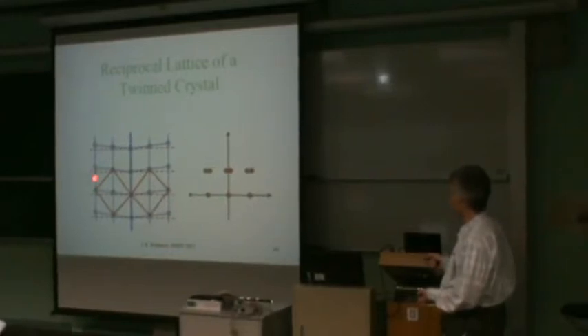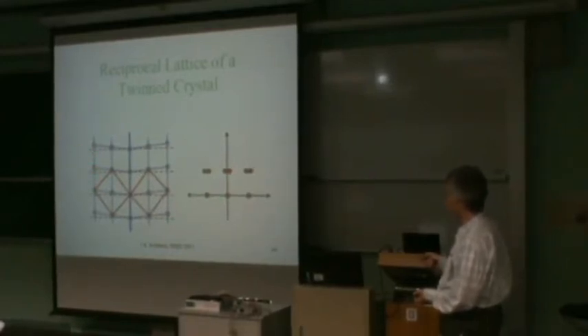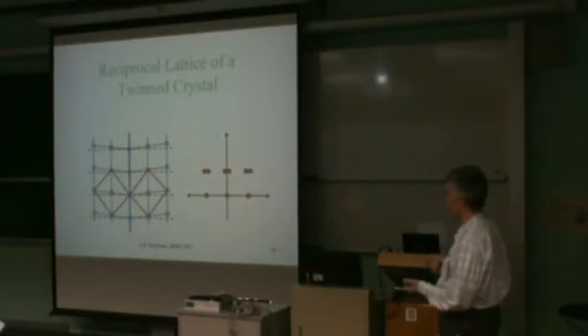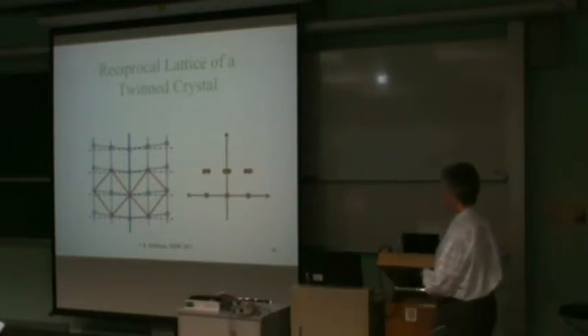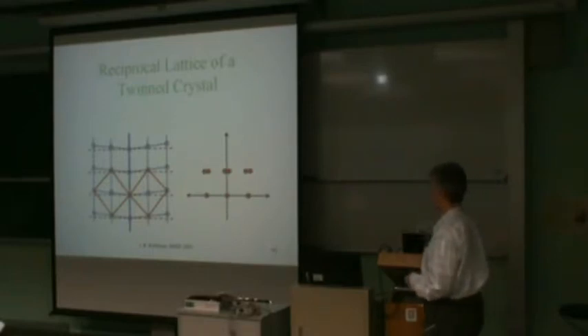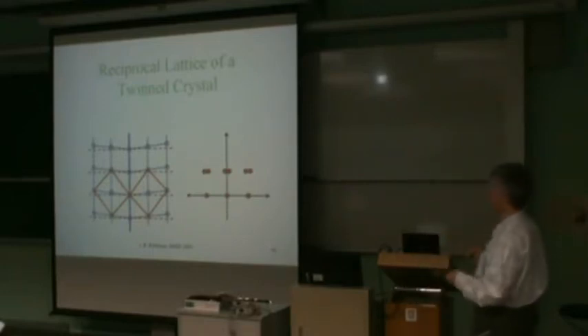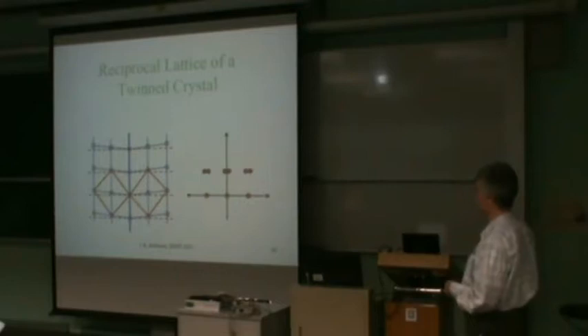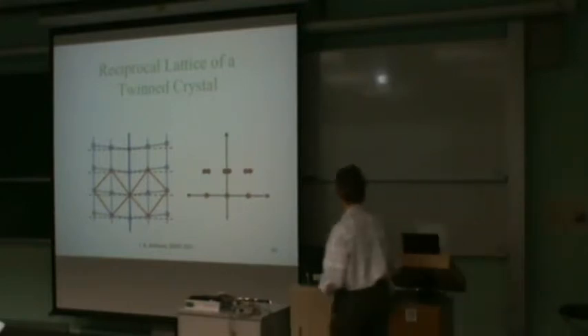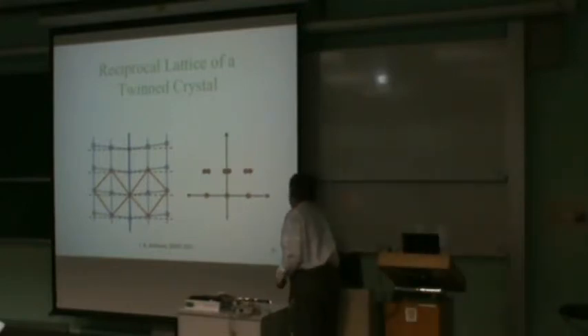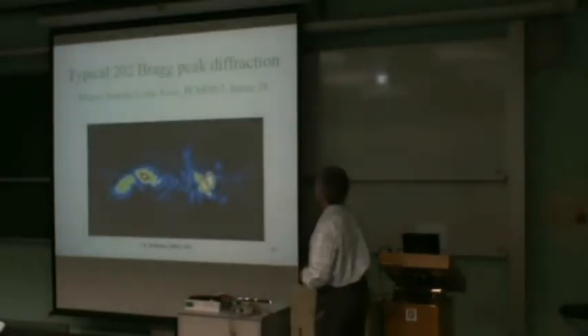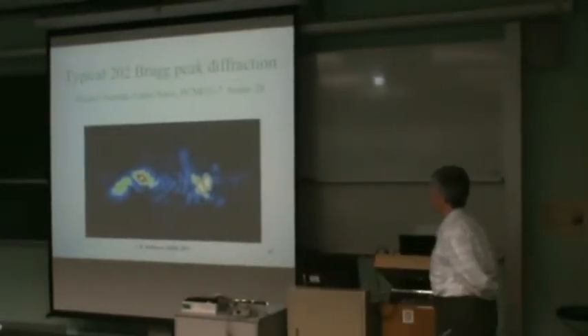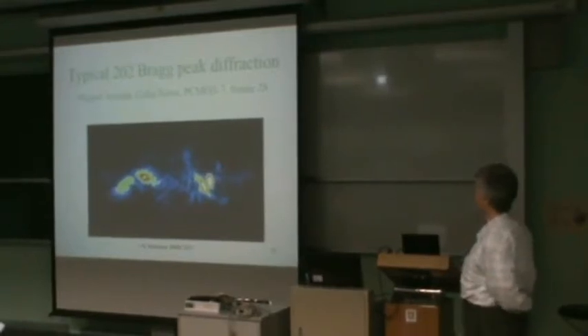But what you have is displacements which get stronger as you get away from the twinning axis, and so you can map this onto a complicated strain field, and what you would expect to see is a pattern. I've got an example to show where you can see what the expected diffraction pattern would look like. So we've been looking for examples of this. It's not a very good one, but this is the best example that we've been able to come up with.